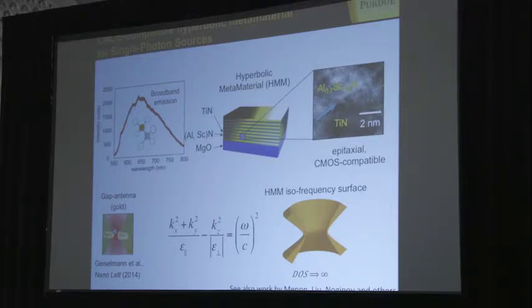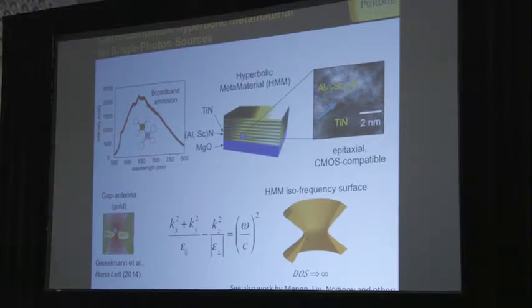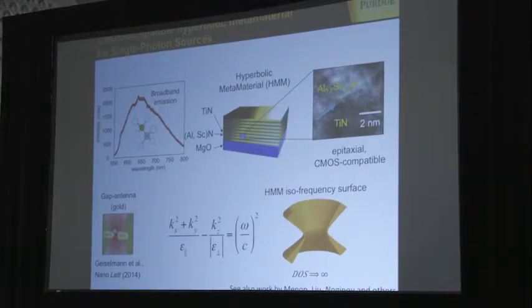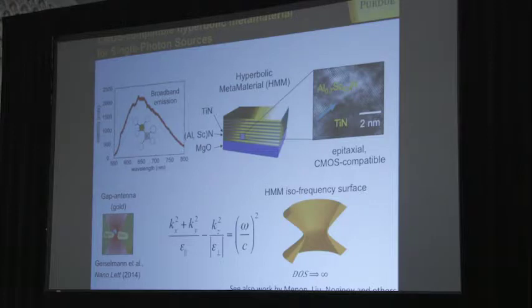of photons. But there is an unorthodox approach, which is using ideas by my colleague Evgeny Narimanov and Zubin Jakob, who also moved to Purdue. So that has to do with so-called hyperbolic metamaterials. These are very interesting materials that have extreme anisotropy. They act as conductors in one direction, actually in two directions, x and y, and as a dielectric in the vertical direction. And you could accomplish this by making very thin layers of plasmonic materials, metallic materials, and dielectric ones. And if thickness is much smaller than the wavelengths, you could average over size larger than the thickness of a single layer, and you would get effective epsilon negative in an xy direction and positive in z direction.